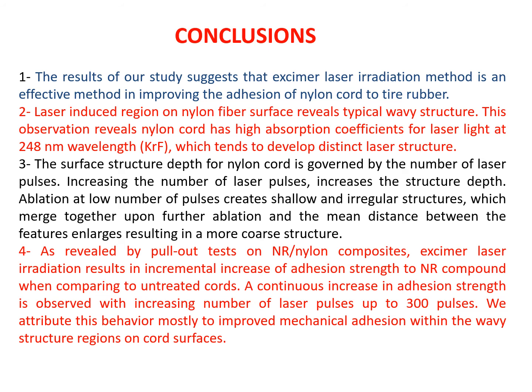Laser-induced regions on the nylon fiber surface reveal a typical wavy structure. This observation reveals nylon cord has a high absorption coefficient for laser light at 248 nanometers, which tends to develop distinct laser structure. The surface structure depth for nylon cord is governed by the number of laser pulses. Increasing the number of laser pulses increases the structure depth. Ablation at a low number of pulses creates shallow and irregular structures which merge together upon further ablation, and the mean distance between the features enlarges, resulting in a more coarse structure.